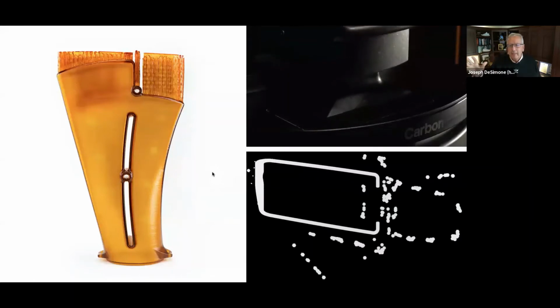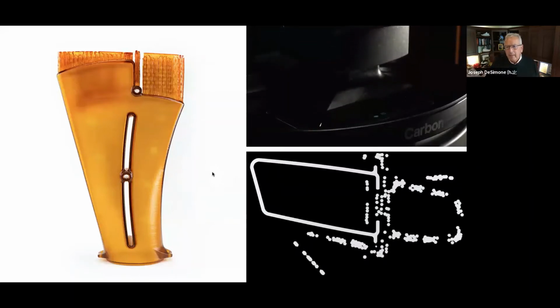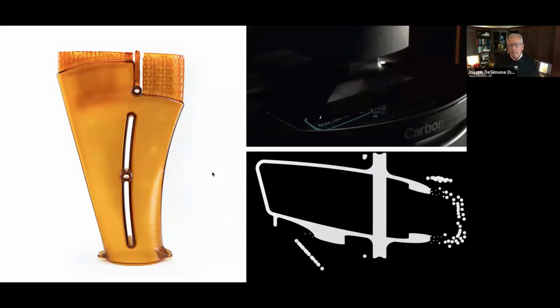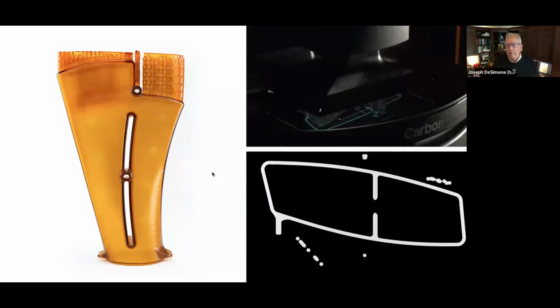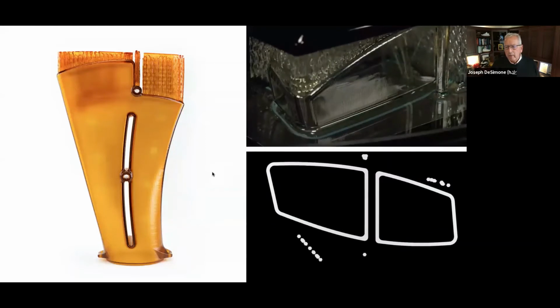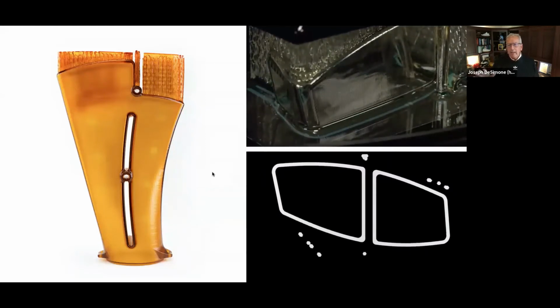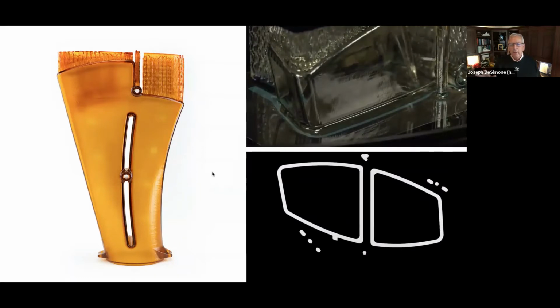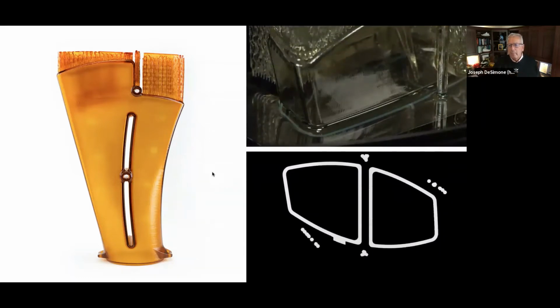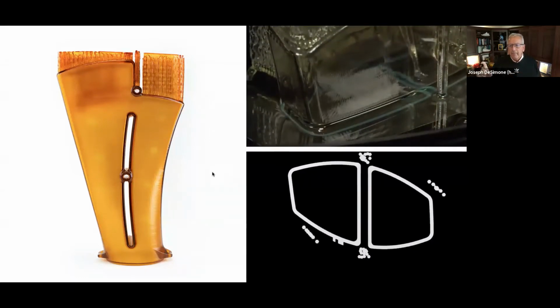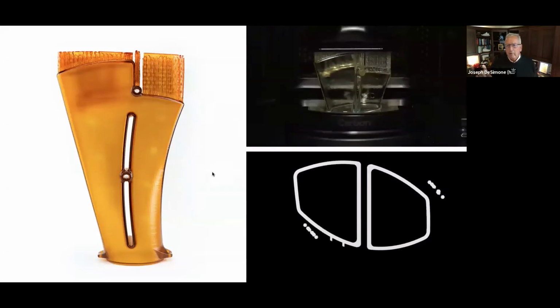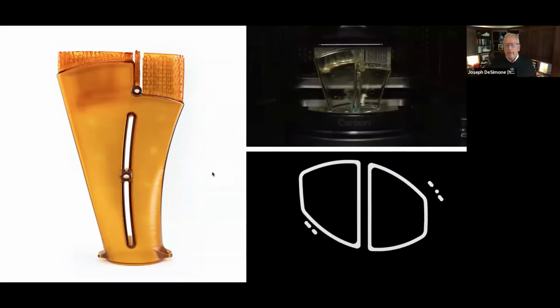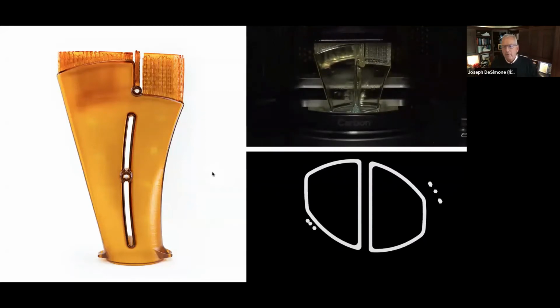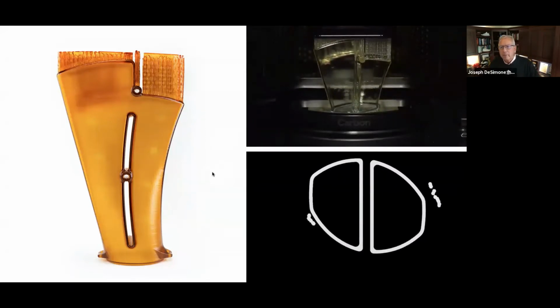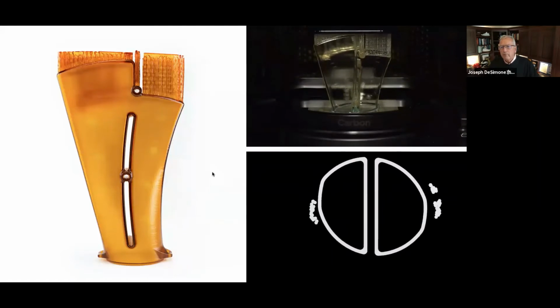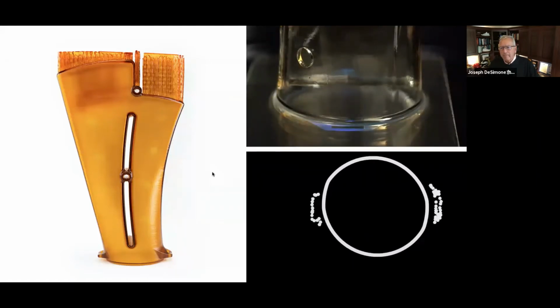So unlike some things in the literature that are misstated, this is not about adhesion. This is about creating a pathway for mass transfer underneath the part. So how do you get a mechanism whereby liquid can flow underneath the part and not be cured, so that you actually can create a mass transfer opportunity? And I'll show you that through optical coherence tomography. So basically, as the part gets pulled up, we're using suction forces to pull liquid underneath the part.